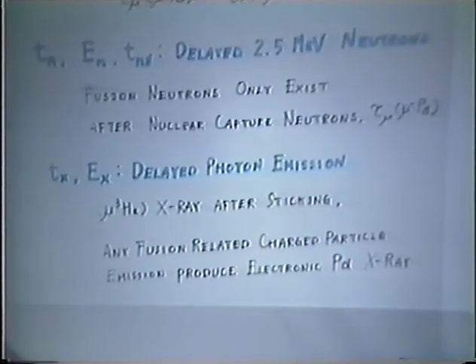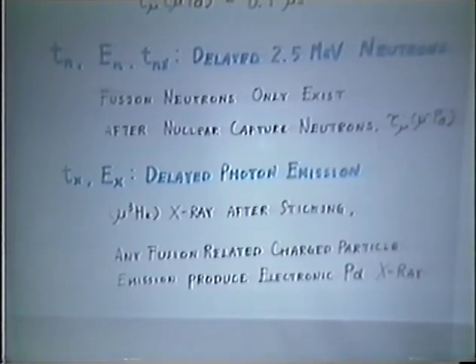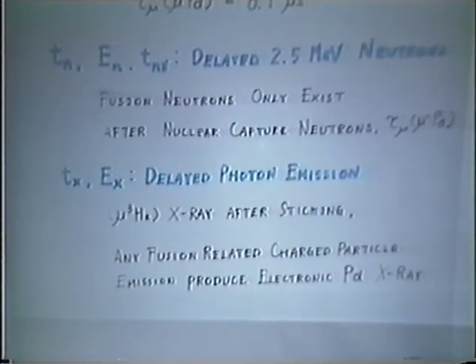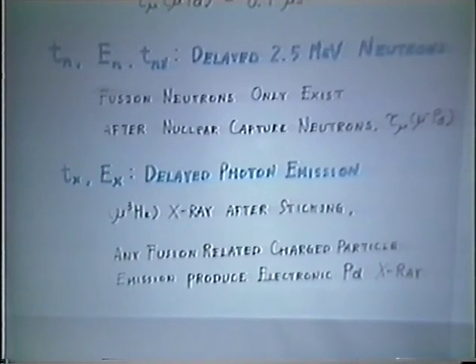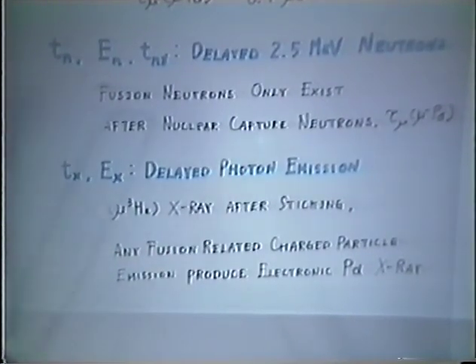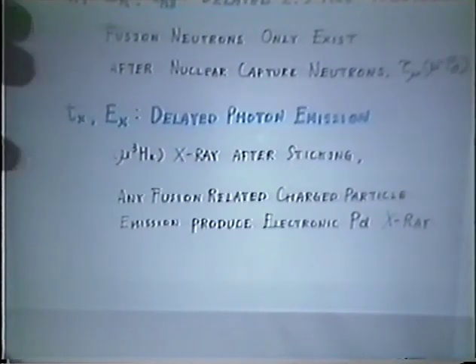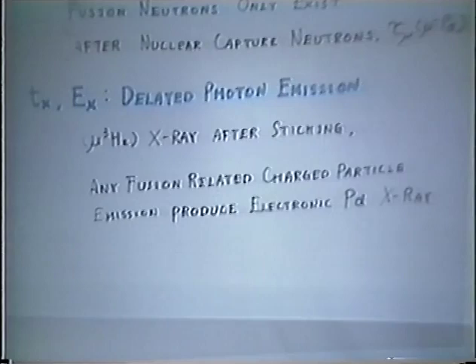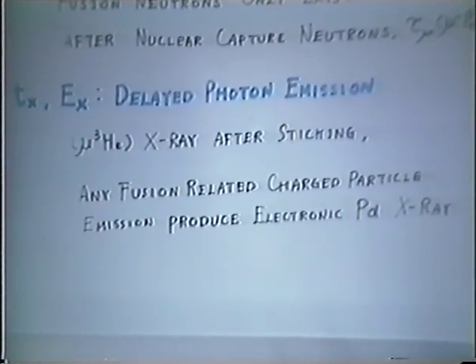Then, in order to search for muon-induced fusion neutrons, we measured the time spectrum, energy spectrum, and gamma discrimination time spectrum for the delayed 2.5 MeV neutrons. And also, in order to measure the fusion-related charged particle effect to produce the electronic palladium X-ray, we measured the timing and energy of the delayed photon emission.